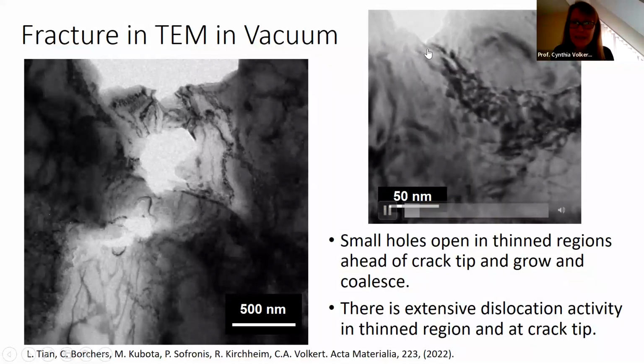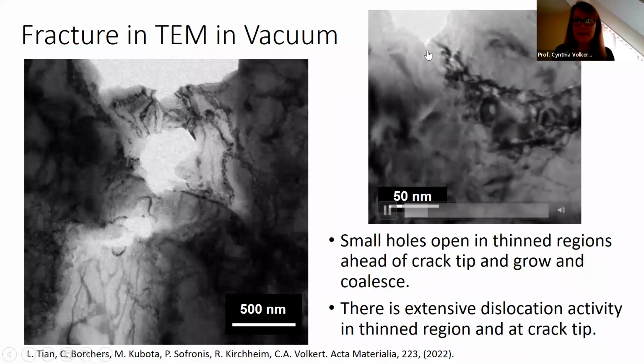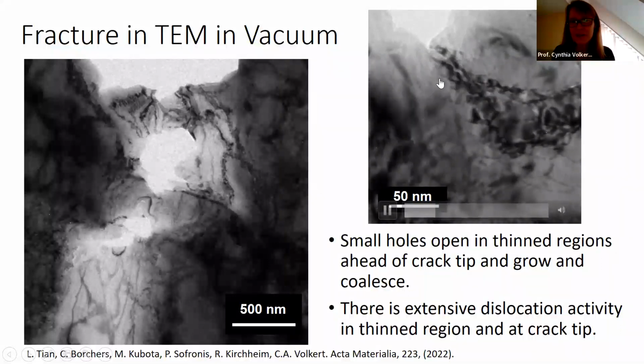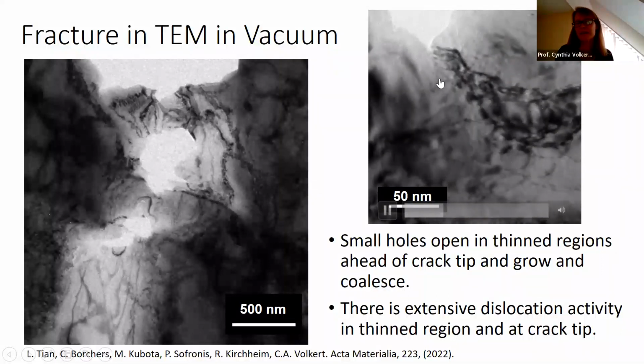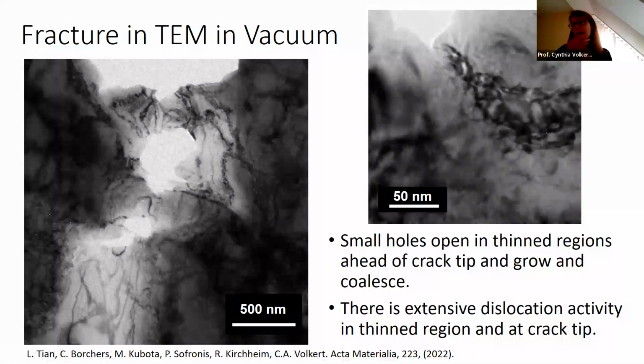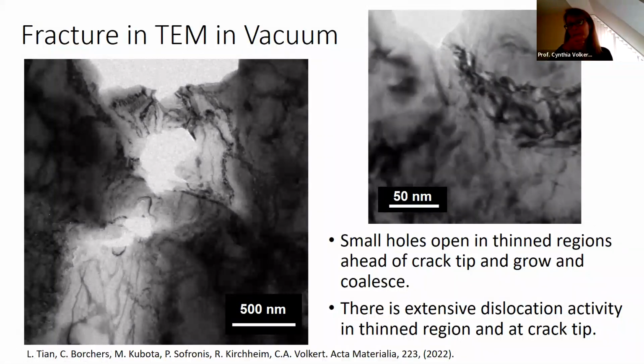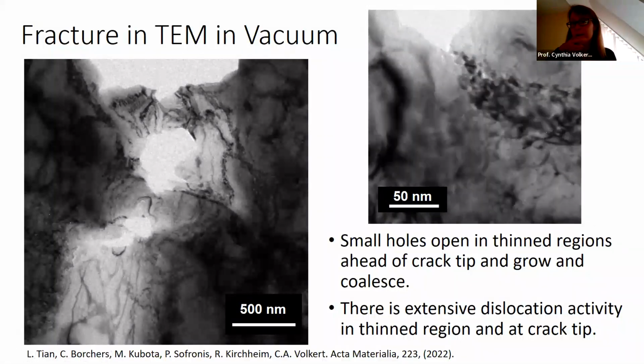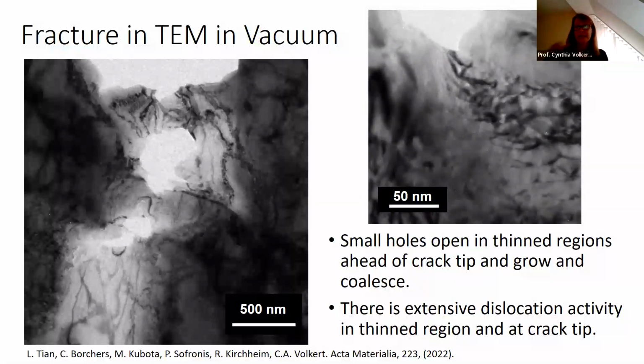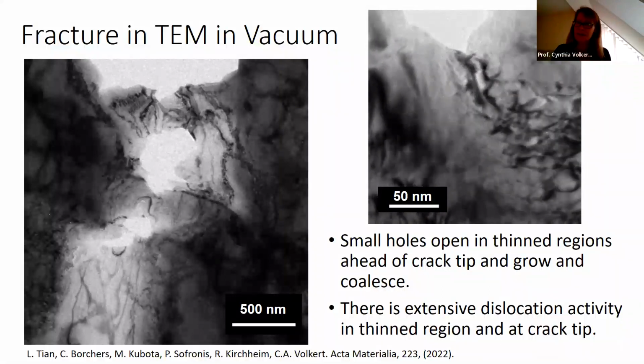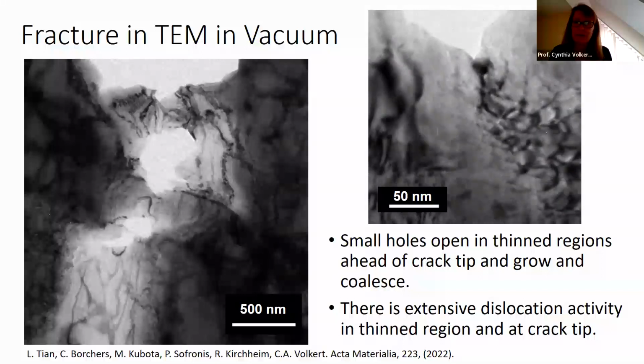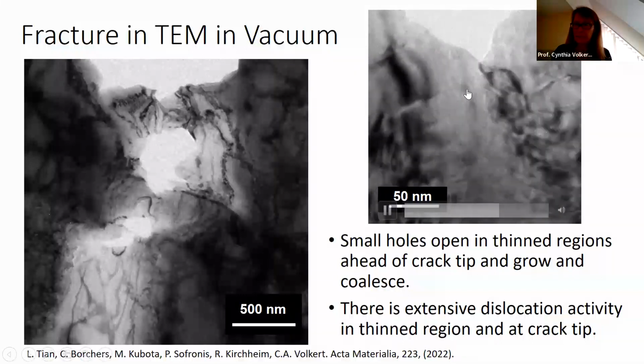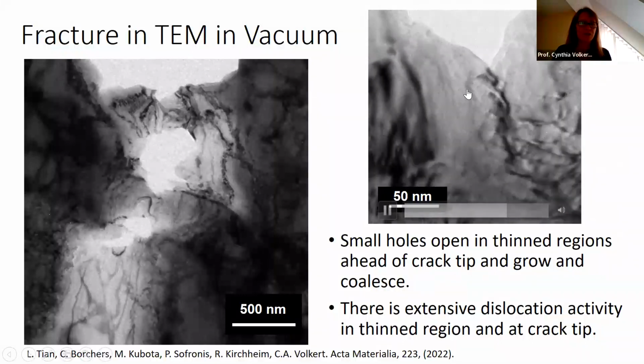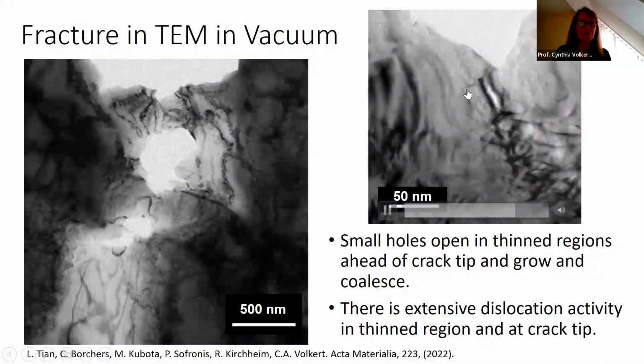And here you can see, in this case, the tip emitting dislocations. Most of the features you see here are in fact the rapid motion of dislocations, and they appear to be being emitted from the crack tip. Okay, so these types of images, Lynn made a number of these tests. What you see here is characteristic of this material.